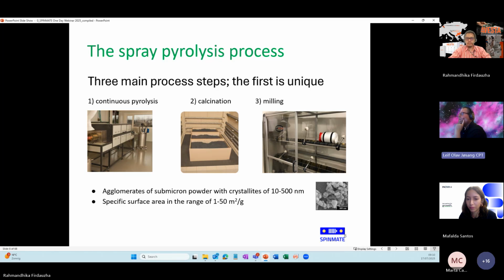We produce agglomerates of submicron powders. The crystallite sizes vary from 10 to 500 nanometers, depending on calcination temperatures and what type of material it is. We achieve surface areas usually in the 1 to 50 square meters per gram area.